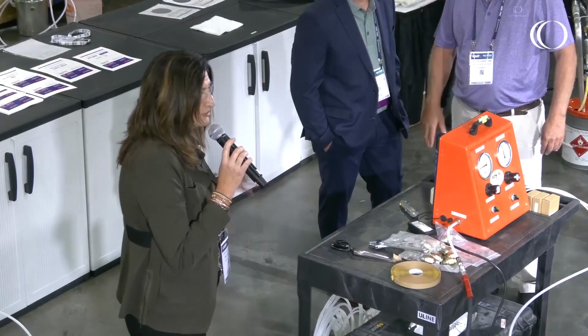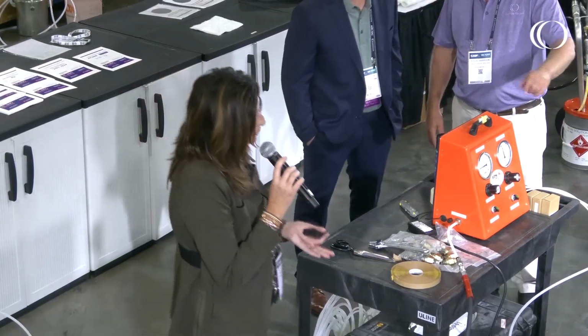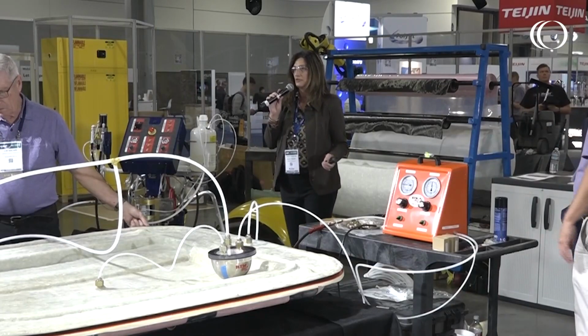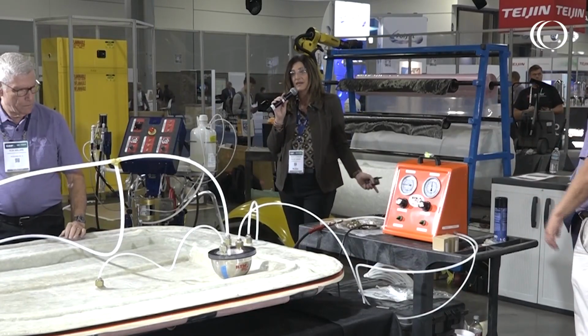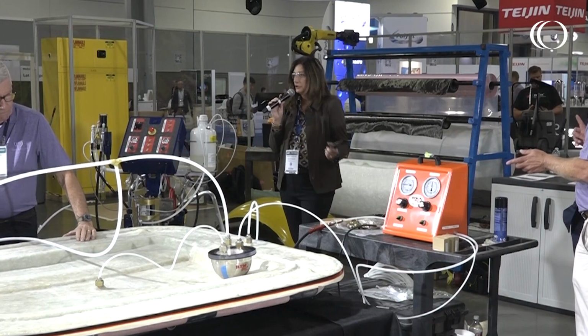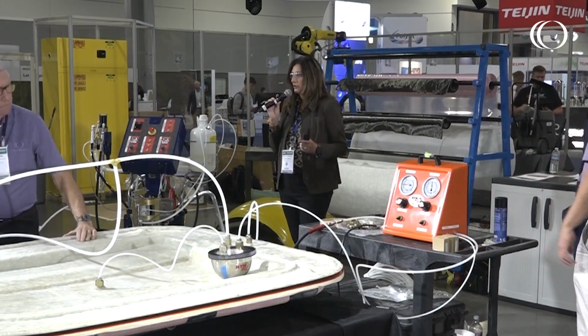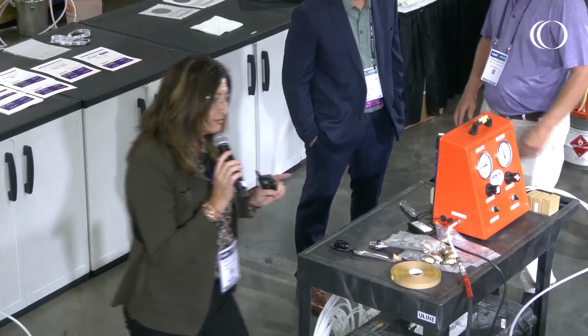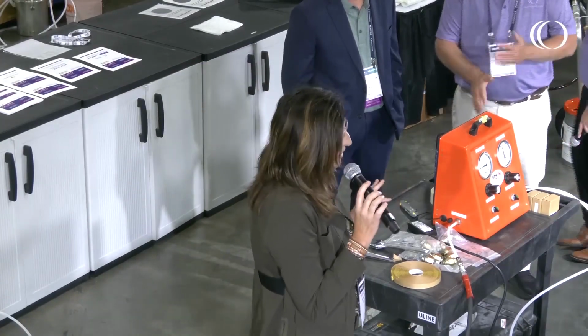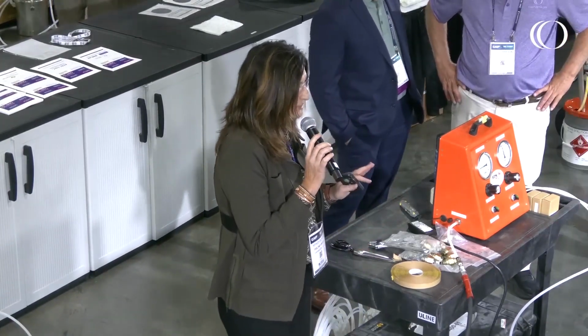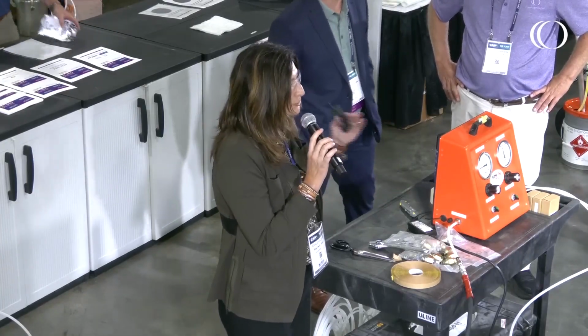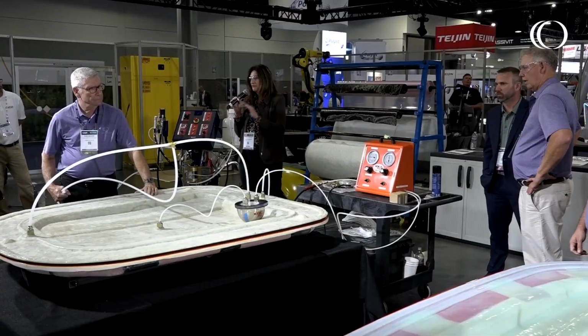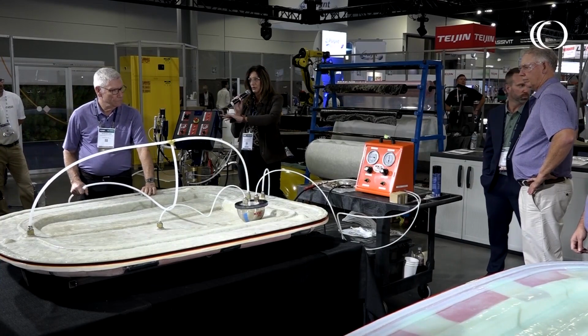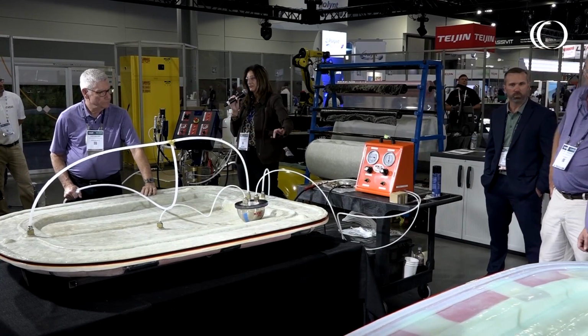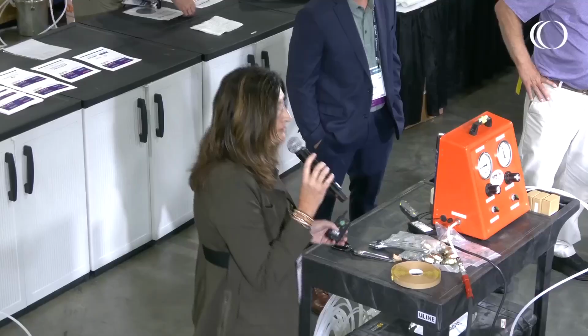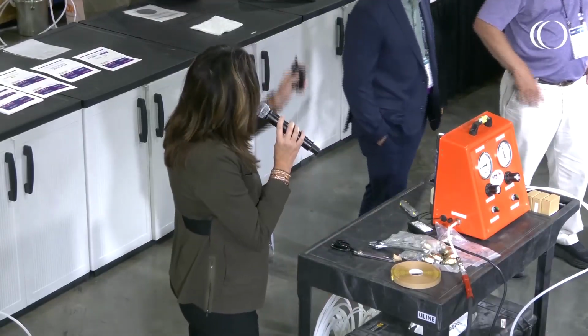The lamination schedule is a typical one that you may see in a marine small part. The resin was initiated with 1.5% MEKP9 peroxide, cured at room temperature, and demolded after an hour after infusing. We post-cured this for 4 hours at 150, but you do not need to post-cure this resin. It's an ambient cure system. We just did it to accelerate our test. After that, we took a BYK wave scan to register the surface profile, and you can see there's virtually no change in the surface profile.